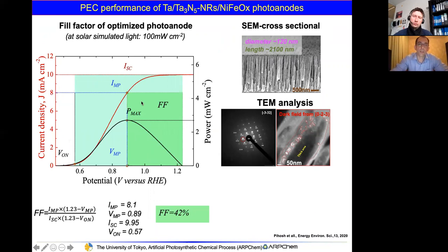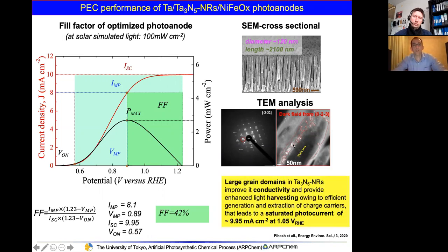So this is actually the first demonstration of the calculation of the fill factor for the photoanode, and we realized 42%. This is due to the big size domain. Actually, large grain domains in Ta3N5 nanorods improve conductivity and provide enhanced light harvesting, owing to the efficient generation and extraction of the charge carriers, which leads to the saturated photocurrent of about 10 milliamp.